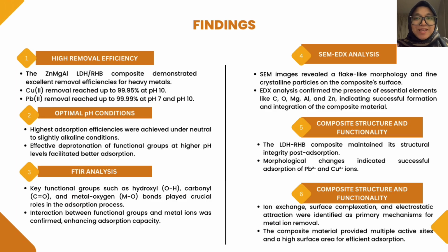Now, let us move on to the key findings from this study on the characterization of the LDH with rice-husk biochar composite in synthetic wastewater. First, this composite material showed exceptional removal efficiency for heavy metals. Specifically, it was observed that copper removal reached up to 99.95% at pH 10. For lead ions, the removal efficiency was as high as 99.99% at both pH 7 and pH 10. These results highlight the composite's effectiveness in adsorbing these ions.